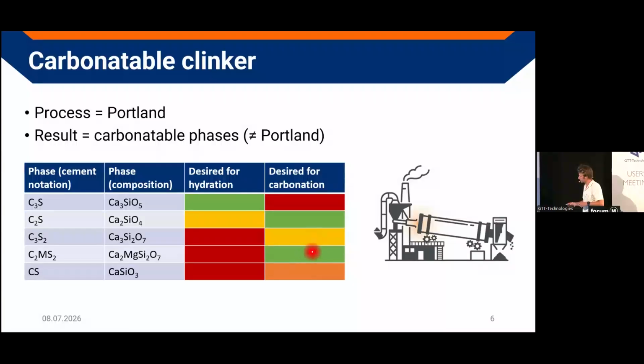Now this calcium-magnesium silicate, that's a little bit more special. That's when you start from magnesium silicates, which are very hard to carbonate. Then you add some calcium, and this phase is the first one you can actually carbonate quite efficiently.